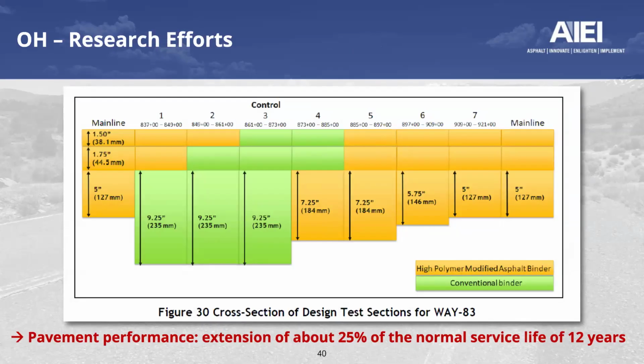that looked at how much of a performance boost do we see with these mixtures compared to other options, the conventional binders. And they found that it was about a 25% increase in life. So about 25% over their normal of 12 years would mean that they're getting about 15 years or more out of these sections.